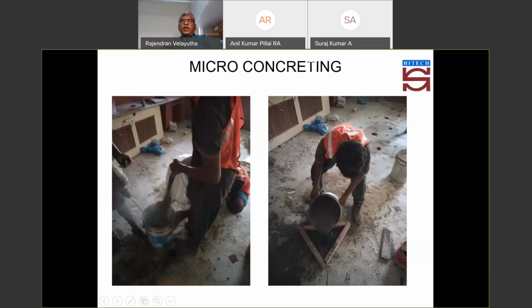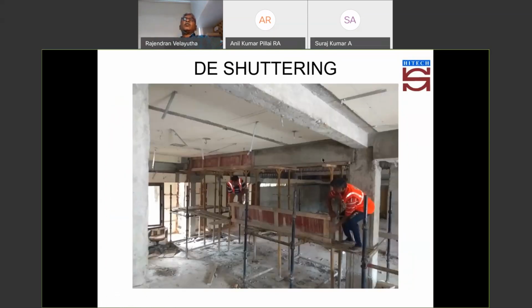As you start pouring the microconcrete continuously, you need to maintain this 100 mm level at the top so that you are making sure the hydrostatic pressure is maintained, and the microconcrete being poured goes from one side and then goes to the other side. There is no problem as far as the soffit of the slab is concerned. After removal, you can find a perfect joint between the slab soffit and the beam side microconcrete.